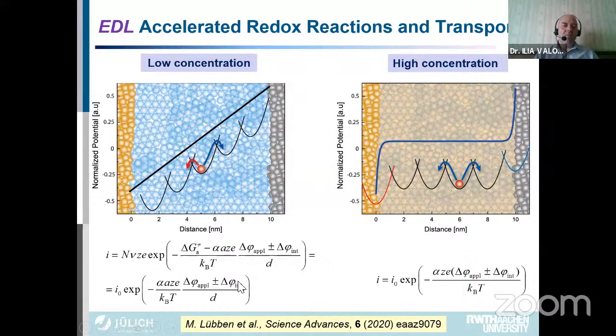So you see the equation here. Important is that you have exponential dependence of the current, whereas normally you don't have this exponential dependence. This is only the classical electrochemical reaction rate. Here the interfaces, but here the transport is driven solely by the Fickian diffusion. So it's a normal diffusion process which is driven from the concentration differences. Here you have field accelerated kinetics, and the mobility of ions is exponentially dependent on the applied field, and also depends on the charge of the ion. So if you have an oxidation state which is higher, let's say if tantalum has 5+, it will be stronger accelerated compared to an electron which has a single charge. So the electric field is differently accelerating the different mobile charges.